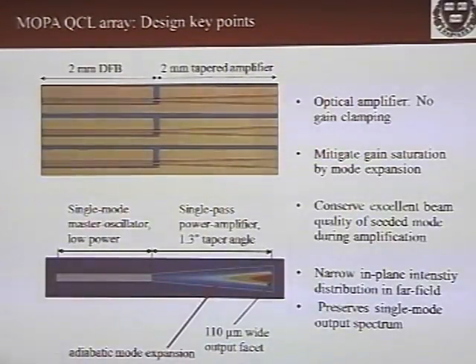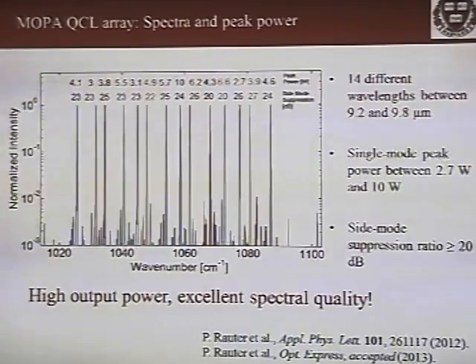The next challenge is to make an array of these devices. So we actually did this again. The key is the adiabatic expansion, and this is just published, so there is a lot of improvement to do, but it's still significant. You see, we have about 15 lasers here, between this wavelength and this. Single mode peak power between 2.7 watts to 10 watts. That's an improvement of over an order of magnitude. If you don't put the amplifier, you can typically get not more than 100 milliwatts from a device with a natural grating. Side mode suppression ratio of most lasers was more than 20 dB. So this is a good start.